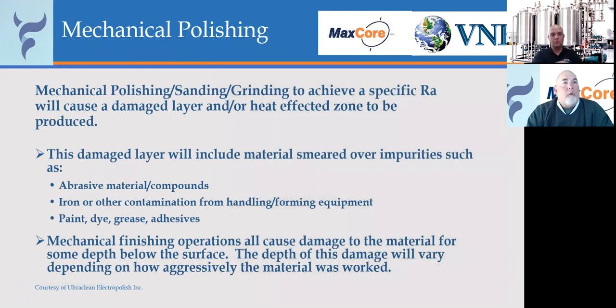Whenever you're doing a mechanical polishing and sanding process in order to achieve an RA value, you're actually damaging the surface of that particular steel. That damaged layer will include things like smeared over abrasives, material compounds, irons, contaminants, paint, dye, greases, etc., all from that mechanical finishing process. And it will actually go down into depths of the material.